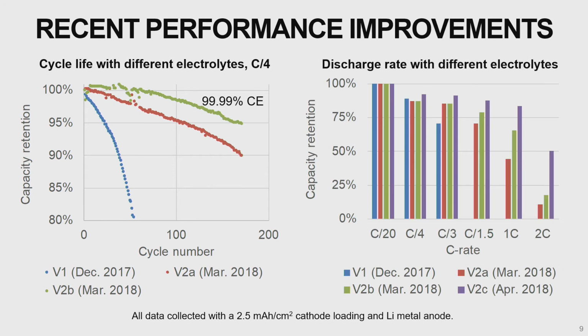In addition, you can also see, I think perhaps most relevant, is on the high power side, which we really need for electric flight. Historically, our chemistry has been somewhat lower power than lithium ion, which has been a downside certainly for any aerial application. So a lot of our effort has gone into not only cycle life improvements, but also power improvements. And if you look at the same electrolytes that I'm showing on cycle life there, you can see in the red and the green, and then particularly in April with the purple, you're seeing substantial improvements in power.